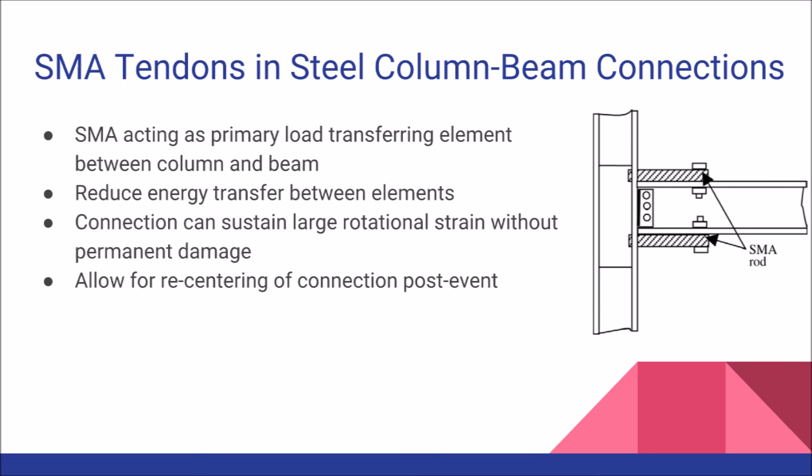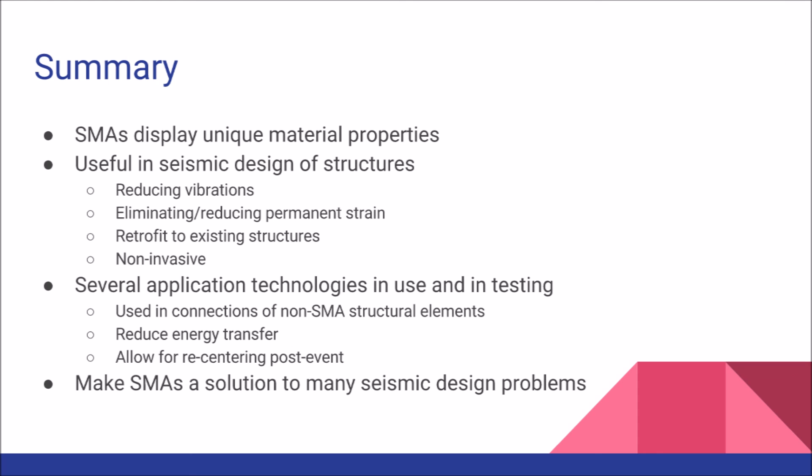Lastly is SMA tendons in steel column-beam connections. Martensite SMA tendons were used as primary load-transferring elements in steel beam-column connections. Based on loading tests of two full-scale SMA-enhanced connections, it was concluded that the connection exhibited stable and repeatable hysteresis for rotations up to 4%, and the SMA tendons were able to sustain up to 5% strain without permanent damage.